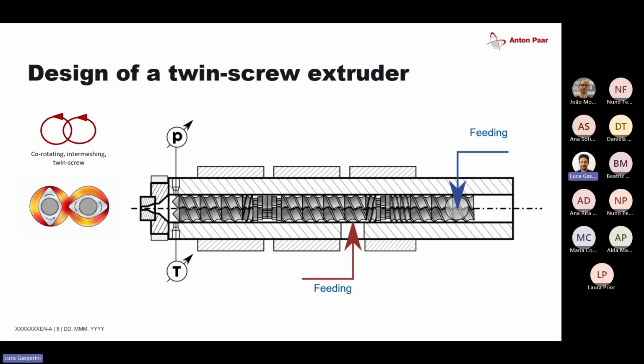And then we have kneading blocks right here, where the material is mixed under high shear. And behind the kneading blocks, we have what we call backwards conveying elements, which basically block the material inside of the kneading blocks from going out until a certain pressure threshold is reached, which increases the residence time, so the mixing time.